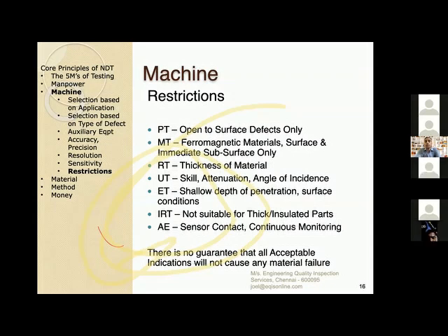And for radiography testing, we have limitations on the maximum thickness. Very complicated radiographic equipment as on date, like Linac and other equipment, can go up to 300 mm. But anything more than 300 mm, radiography testing will not help you at all. You will not be able to find any defect on a material that is more than 300 mm in thickness.